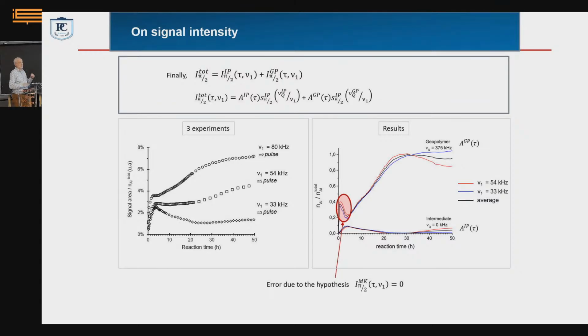But by doing different measurements, always in the liquid state, but with different pulse power in the NMR experiment, we can recover the amount of aluminum in solution at a given time and the amount of aluminum in the NASH gel or the geopolymer. You choose your wording, I don't care, okay? And you see that it's relatively linear. After a certain moment, you come to completion, but this is relatively linear. So this is interesting because this is not at all what we see, for instance, when we hydrate alite, where we have this sigmoidal behavior. Here we have a really linear behavior. The problem is that at a very short time, there's still a lot of metakaolinite in the system.